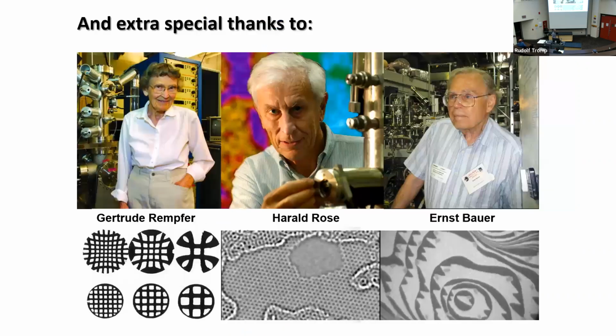And finally, I should thank the three elders in the field. Gertrude Rempfer, who first showed that you can use an electron mirror to do aberration correction. For those of you who use aberration correctors here, right, you have this multipole optics, and there's like 80 coils that you've got to balance and adjust, etc. 80 power supplies. Here, with three elements, you can not only do CS, but you can also do CC with a very simple piece of optics.